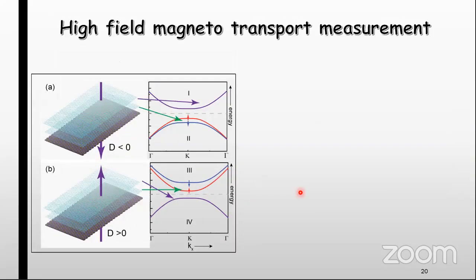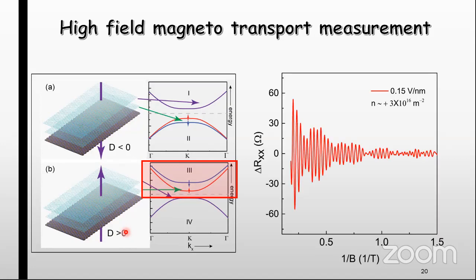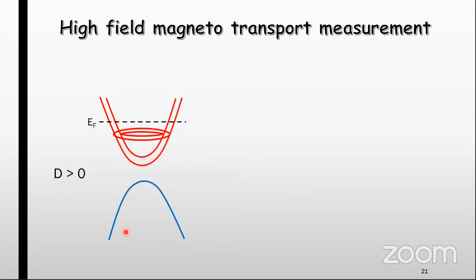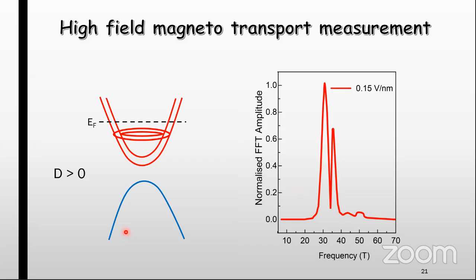Further, to probe the splitting, we performed a high field magnetoconductance measurement. We sit in region 3, which is the conduction band for positive value of D. We performed Shubnikov-de Haas oscillation measurements, and we found the presence of beating, which says that there are 2 Fermi surfaces present in the conduction band. So that should look like this. When we did an FFT for that, we found 2 frequencies present, and that again says that 2 Fermi surfaces are present.